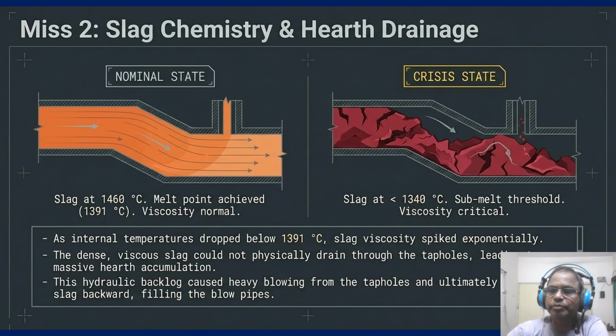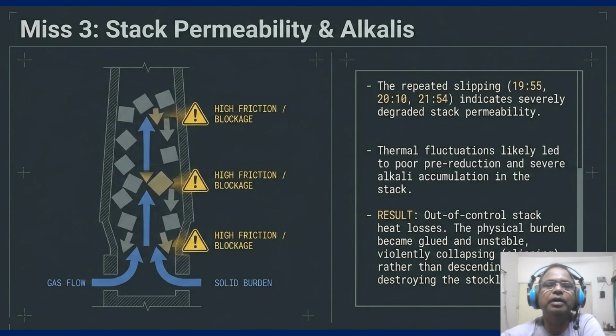So coming to our next miss, that's miss number 3, and this is about stack permeability and the alkali. So the visual on slide 11 shows the internal burden with high friction and blockage icons highlighted in yellow. The repeated slipping at 19:55, 20:10 and 21:54 is the smoking gun for severely degraded stack permeability. So thermal fluctuation likely led to poor pre-reduction and severe alkali accumulation. So as alkali recycle in the stack, they create a glue that prevents the burden from descending smoothly.